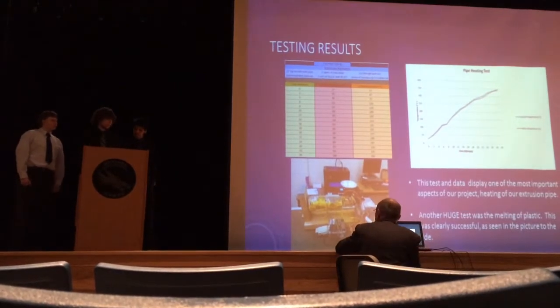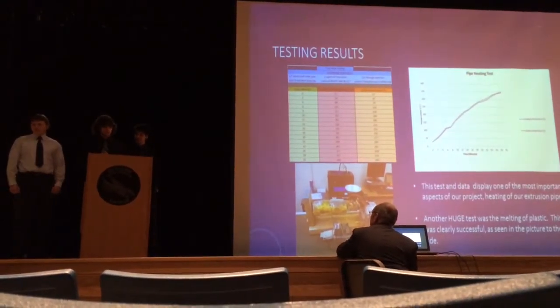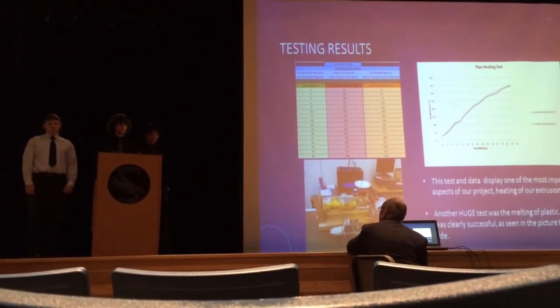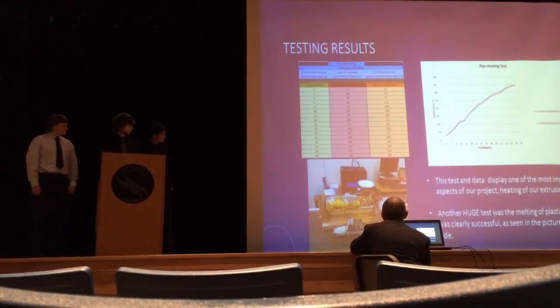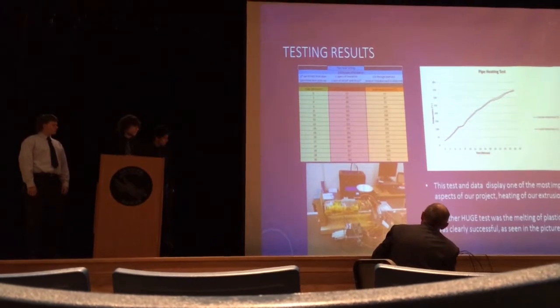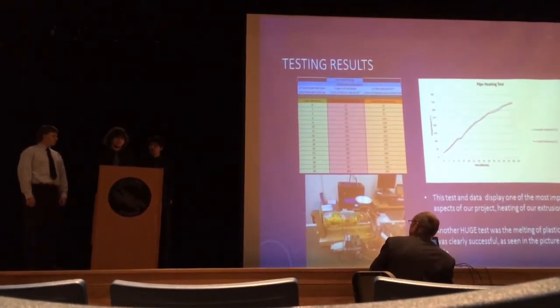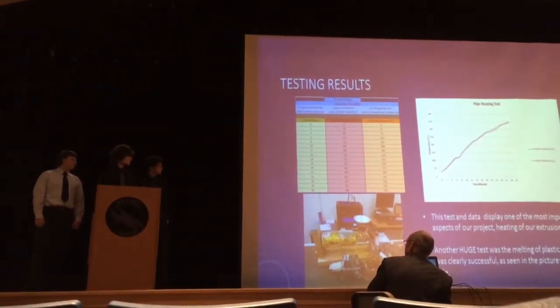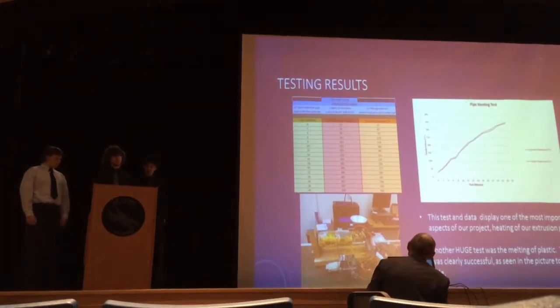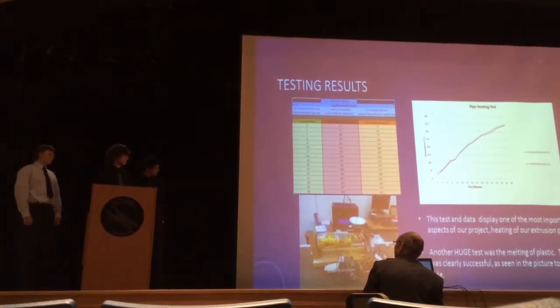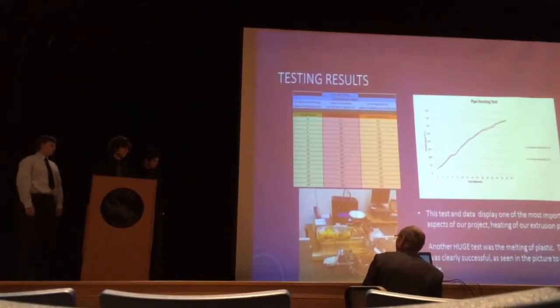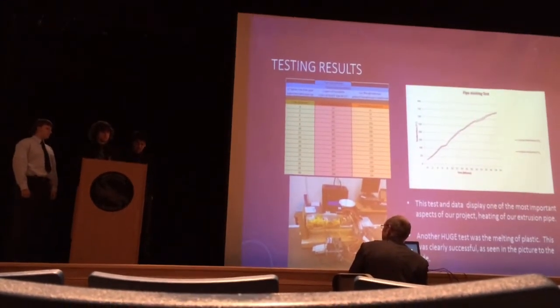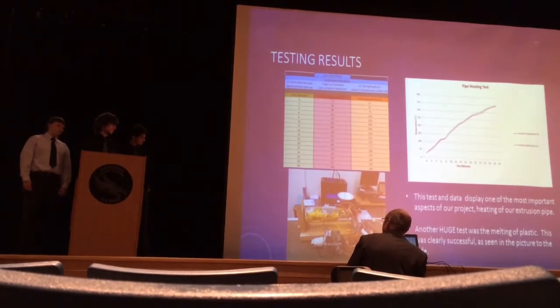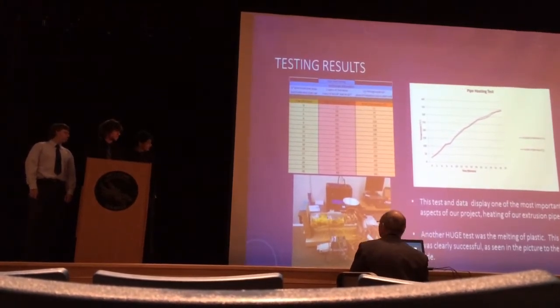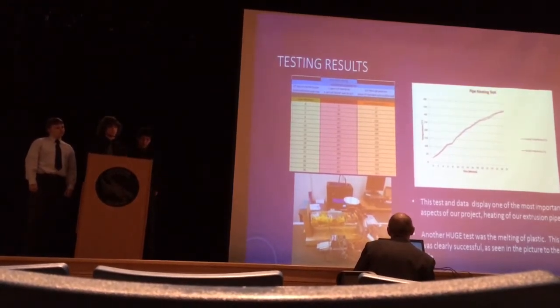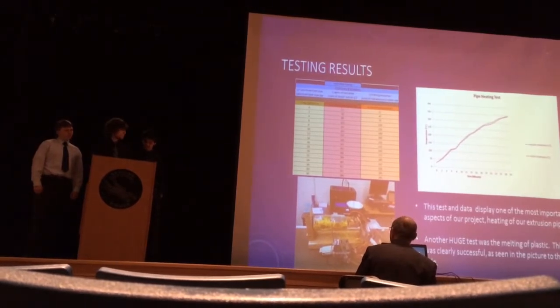And then the other large test that we did was the actual melting of plastic, the melting and extrusion of plastic, and that took quite a while, because with our auger, what happened was it's not quite long enough, I guess, and to test the extrusion of the system, what we had to do is we had to put plastic in the funnel, and we would push it down and allow it to melt, and then we would push it through into the auger with a screwdriver, and that was pretty tedious, and it took a long time, but we were successful in melting and getting the plastic to not quite extrude, but get to move through the system. We never got it to actually extrude though, sadly.